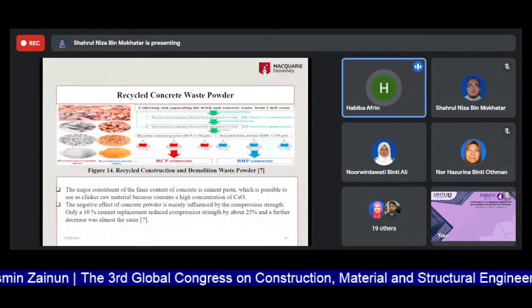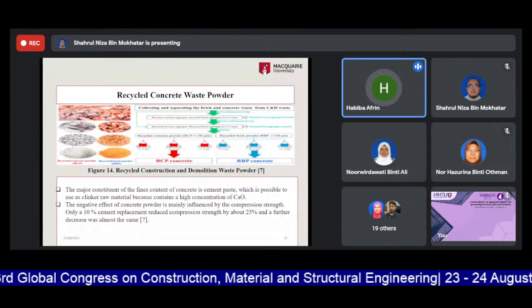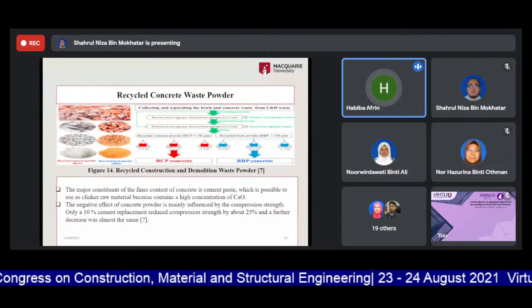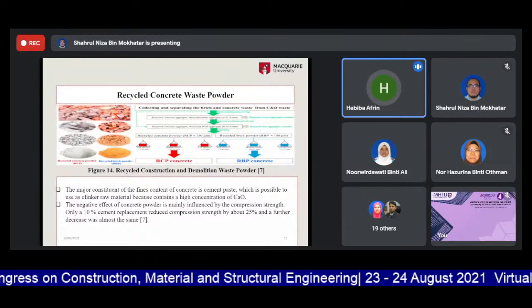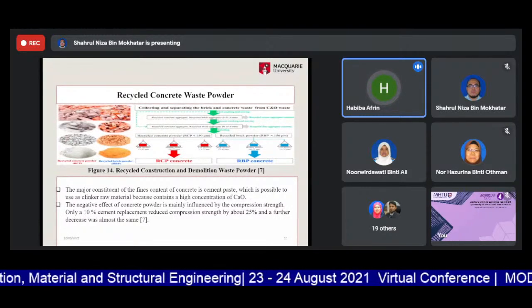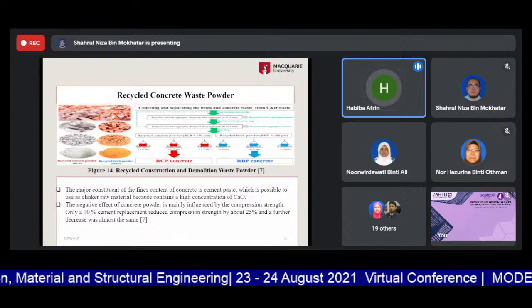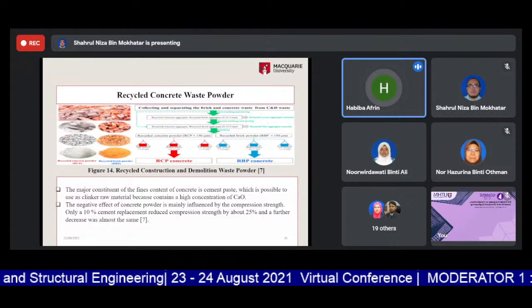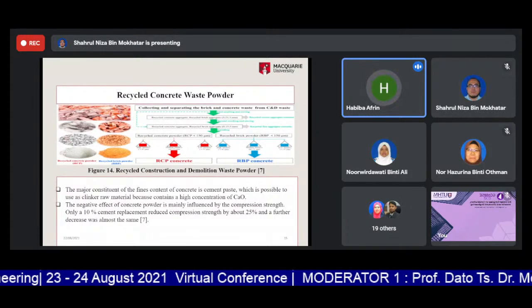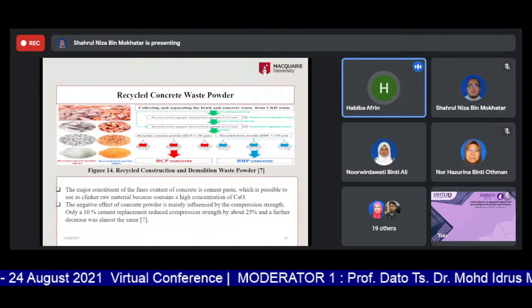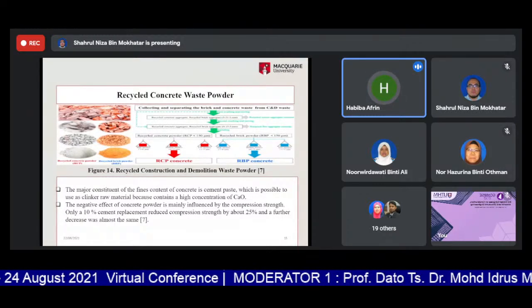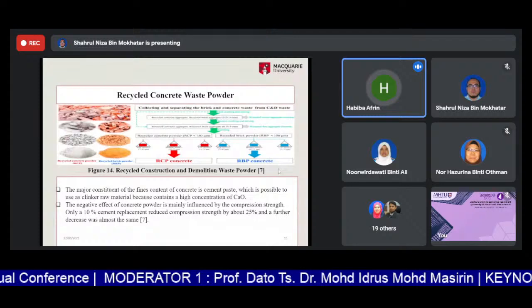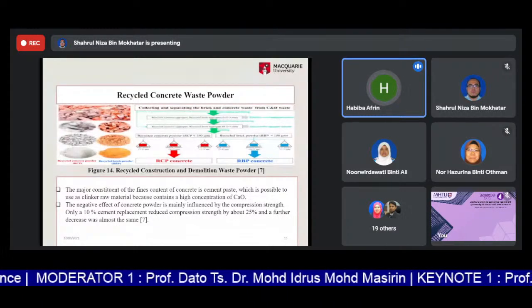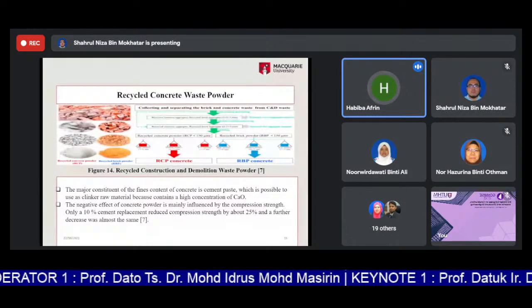We can use concrete powder as well and brick powder as a replacement of cement. The major constituent is the fines content of concrete in cement paste, which is possible to use as a clinker raw material because it contains a high concentration of CaO. The negative effect of concrete powder is mainly on the compression strength. Only a 10% cement replacement reduced the compression strength by about 25%, and a further increase was almost the same.